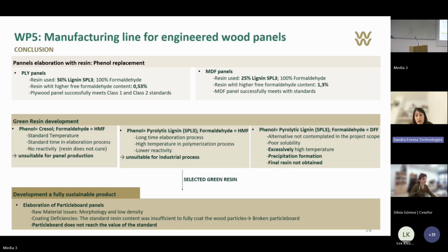To elaborate these, we had to increase the resin content and press cycle, despite the low density of the chips. However, the panels did not reach the standard. Nevertheless, this represents a successful proof of concept, as the results show it's technically possible to elaborate panels with 0% formaldehyde and 0% fossil phenol.